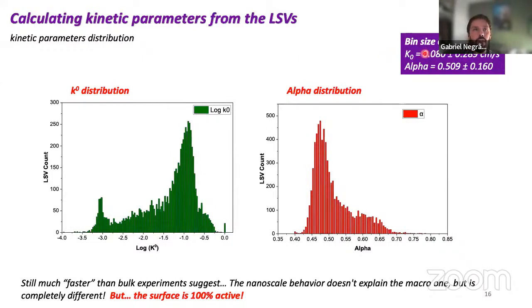Far from expected. I think I forgot to mention, for conductive materials, we assume that K0 is at least 1 centimeter per second or more. It depends on the transport rate of your technique, what's the top end that you can simulate or detect. But anything at 10 centimeters, 100 centimeters per second is all going to be very reversible, very fast. But the calculated one here is 0.08, which is off what we expected, just showing that it's a slowish surface than expected, with a group here that is very slow. Alpha is in the ballpark of 0.5, so not much comment on that, especially because it's hard to argue why it would not be alpha in this case.